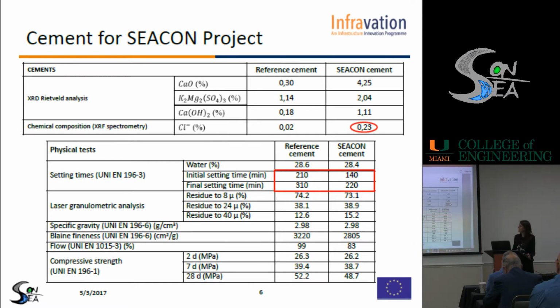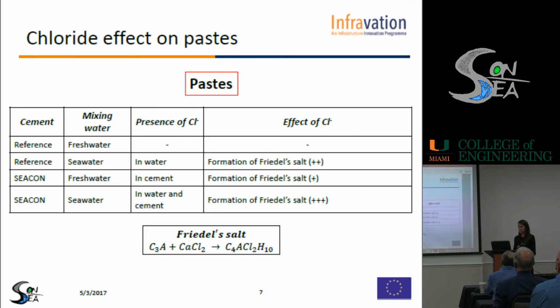So we performed the characterization of the two cements to understand the effect of this very high chloride content, and we can see that the main effect is on the setting times. So we can say that the high chloride content can have an acceleration effect in this case. But we decided to continue this investigation, so we produced pastes, so cement plus water, and we considered the two cements with both fresh water and seawater to understand the effect when chloride is present in the water, in the cement, and in both water and cement.